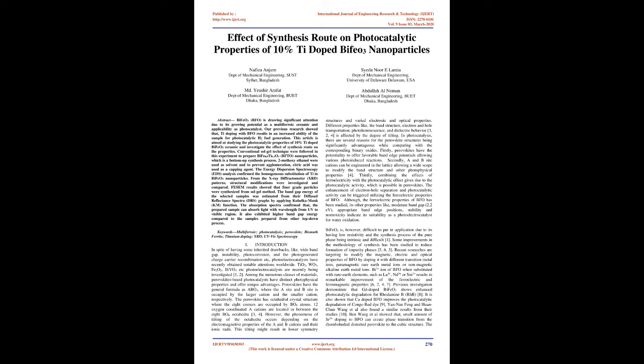The bandgap energy of the selected samples was estimated from their diffuse reflectance spectra, DRS, graphs by applying the Kubelka-Munk, KM, function. The absorption spectra confirmed that the prepared sample can absorb light with wavelengths from UV to visible region. It also exhibited higher bandgap energy compared to the samples prepared from other top-down processes. Keywords: multiferroic, photocatalysis, perovskite, bismuth ferrite, titanium doping, XRD, UV-vis spectroscopy.